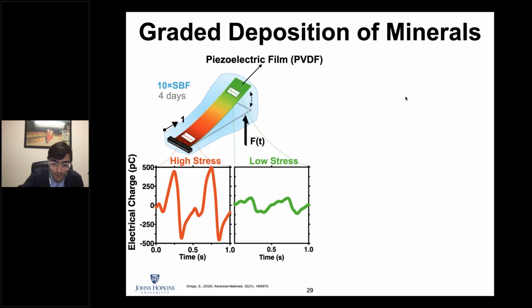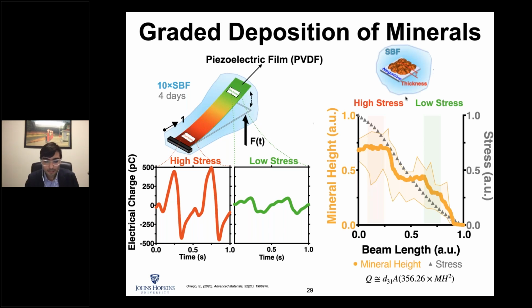So it's great. Then we put this film into the same SBF mineral environment, with a lot of calcium ions available, and then we measured how much minerals we were depositing, in terms of thickness, along the axis of the beam. This is what we're showing you here.